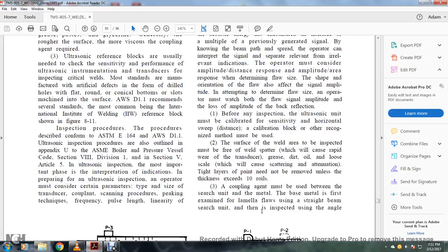One. Before an inspection, the ultrasonic unit must be calibrated for the horizontal sweep and distance; the calibration block or a recognized method must be used. The surface of the welding area to be inspected must be free of weld spatter, which will cause rapid wear of the transducer, and of grease, dirt, and oil, as well as loose scale, which will cause scattering and attenuation. Tight layers of paint need not be removed unless their thickness exceeds 10 mils. A couplant agent must be used between the search unit and the metal.